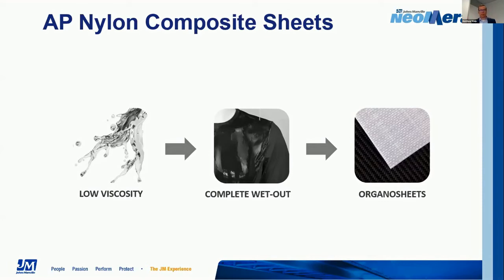So it's nylon 6. It's a very common, well-known thermoplastic material used in many different places. And for our customers and people who use the product, they're not going to really notice any difference between that and a melt impregnation from a polymer standpoint. Maybe the only benefits would be on the positive side. So by applying that low viscosity system to a fabric, it's then polymerized, and then we produce our Organosheet. And it's a sheet-based product, so that's what we're producing. And it's a continuous process. So we start from fabric, and it becomes a continuous ribbon of product that becomes an Organosheet on the other side. And then right now we chop those into sheets, and that's our product that we sell into the market.